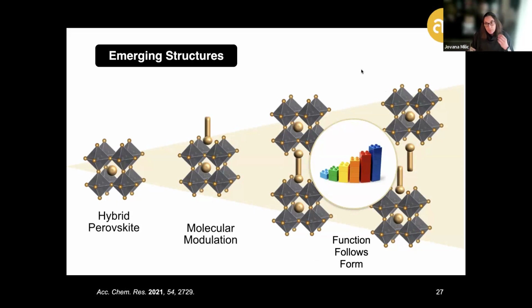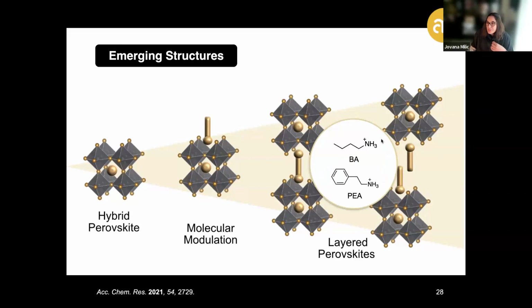So far, these systems have primarily involved relatively simple organic molecules that can template such layered structures, represented by two archetypical structures primarily used in the Ruddlesden-Popper phases that are predominant: the butylammonium system, having an ammonium terminus to anchor to the inorganic phase with the alkyl chain forming the organic layer templating the rest of the system, or the phenylethylammonium system that enables the same through further tailoring of interactions via the pi-based interactions of the aromatic system.